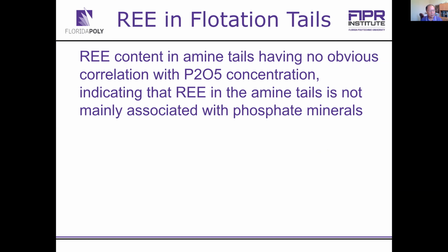So our research first was to understand the occurrence of rare earth elements in each of the process and streams. First, we investigated flotation tailings, mainly the amine flotation tailings. We found that the rare earth elements concentration does not have obvious correlation with the P2O5 content. That means there should be rare earth minerals instead of just calcium substitution in the phosphate crystals.